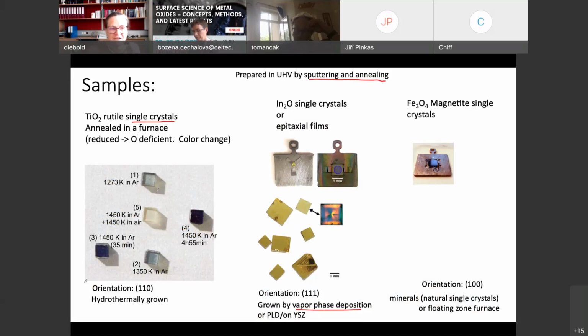And then what you can see is once we take out oxygen, we dope them, we take out oxygen, put in indium, that leaves behind extra electrons, it becomes opaque, it becomes really dark. So this one doesn't have this nice property as the indium oxide. But if we just reduce it a little bit, take out a little bit of oxygen, they become light blue, and they're pretty conductive already at room temperature.